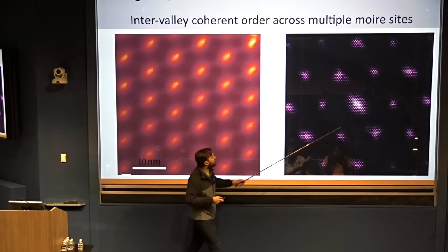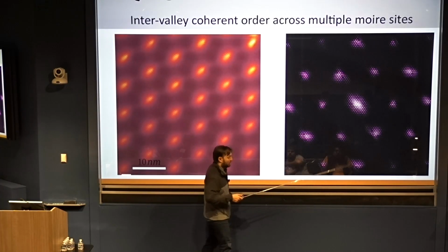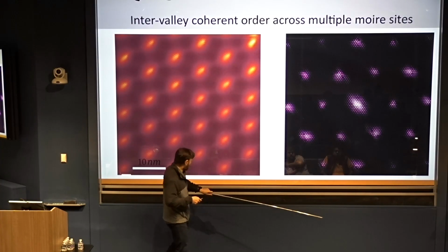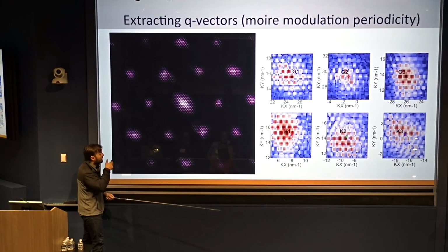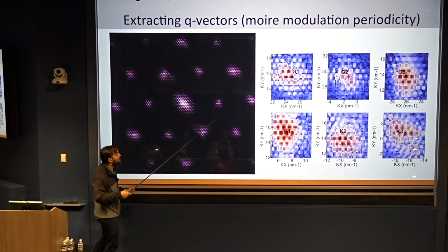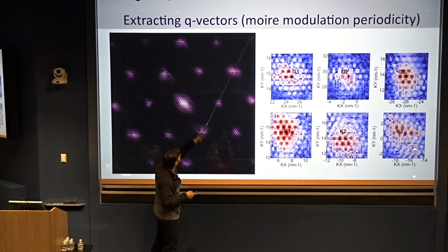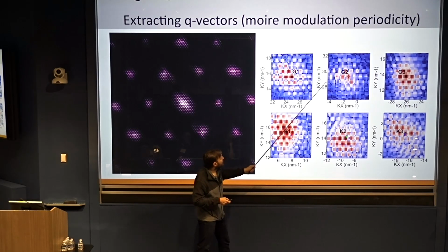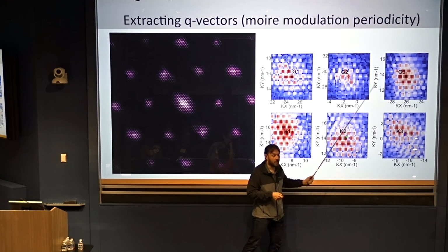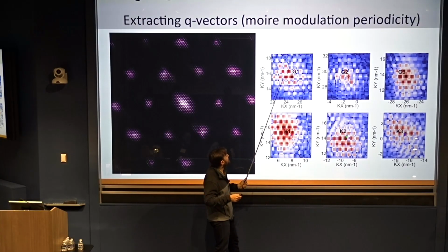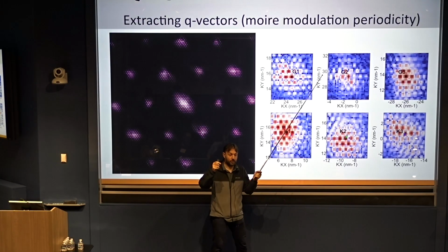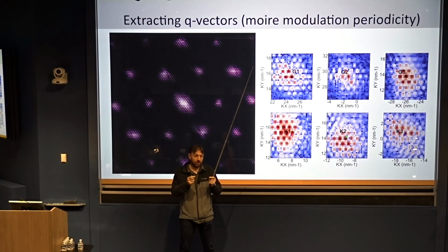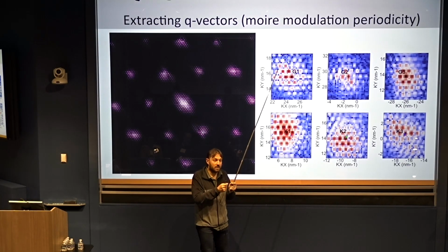So now each of these images is converted into a selection of dots. I'm going to skip some details, but based on the analysis of these peaks, and higher order peaks that happen, for example, here and beyond, you can actually calculate where the real graphene peaks reside. Then you can use these real graphene peaks, which correspond to the graphene atoms' periodicity, to calculate where the square root 3 by square root 3 reconstruction would sit in momentum space.